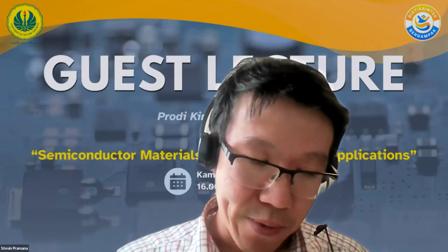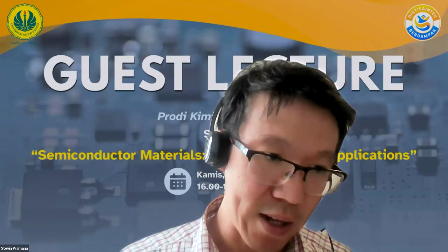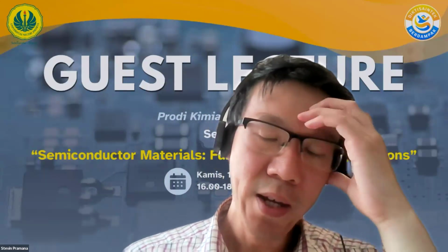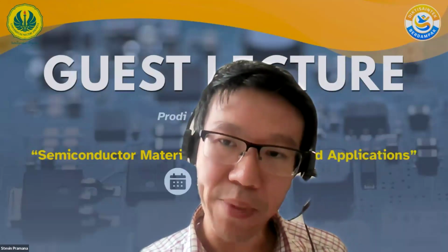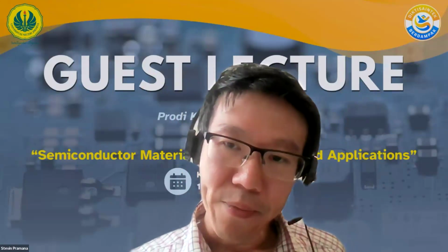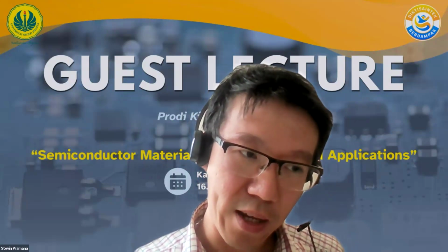So in a typical case, for example, catalyst for, let's look at, the oxygen reduction reaction in, let's say, alkaline condition. So for water splitting or electrolysis, let's say if you've got perovskite, lanthanum cobaltate, then typically they are P-type semiconductors. The way sometimes we can tell that also is if you have a facility to control the oxygen partial pressure, for example, because the conductivity is going to be different at different oxygen partial pressure, because the oxygen vacancy on that particular perovskite is determined by the PO2.